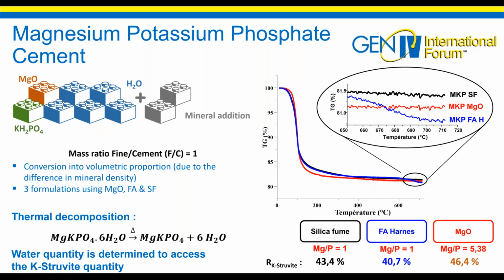The results at 7 days give a yield of 43.4% for silica fume, 40.7% for fly ash, and 46.4% for magnesium oxide. This confirms the physical role of excess magnesium oxide in these matrices. This difference is due to the approximation. And in the case of the magnesium oxide matrix, the difference comes from the fact that more magnesium oxide is available to react. The difference in mechanical performance would then come from the quantity of struvite.